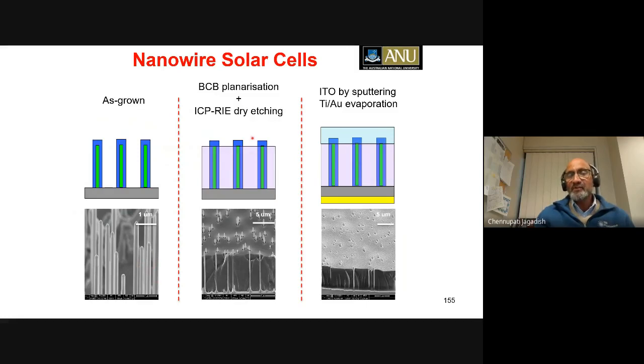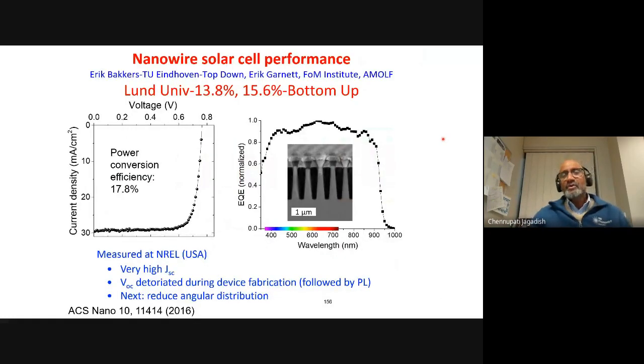a BCB polymer and selectively plasma etch it to expose the tips, put some indium tin oxide at the top and then the metal contacts at the bottom, and then shine light and look at the light emission, look at the efficiency of the solar cells, for example, the current generated. Again, to cut the long story short,